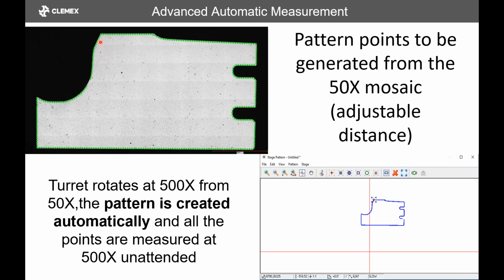Then we go here and generate some dots. We have a tool that will generate pattern positions. Each of these green dots here will be measured by the system. In this case, it could be a bit overwhelming that there are so many, just to show that we can detect all the layers of the coatings everywhere around it. But they could be spread out. Now the turret turns to 500x from the 50x original, and then the pattern is created. So this is this pattern here. All of those are dots that will be scanned at 500x.